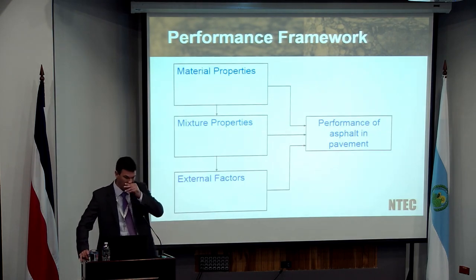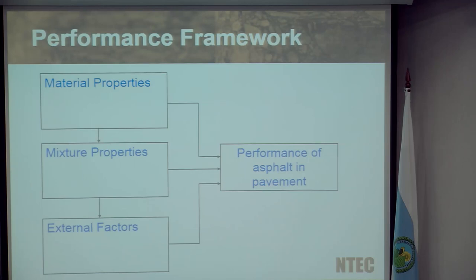So we set up a framework of trying to understand what were the key drivers in terms of looking at moisture damage. And effectively, we looked at three different areas: material properties, mixture properties, and finally what we call external factors. So the material properties are fairly self-explanatory. This is looking at the material composition, the components, the stone, the bitumen, and determining their physical as well as their chemical properties. And this is important because although it's a physical phenomenon, inevitably because of the reaction between a stone or an aggregate and bitumen, there is a chemical aspect to what we are looking at.